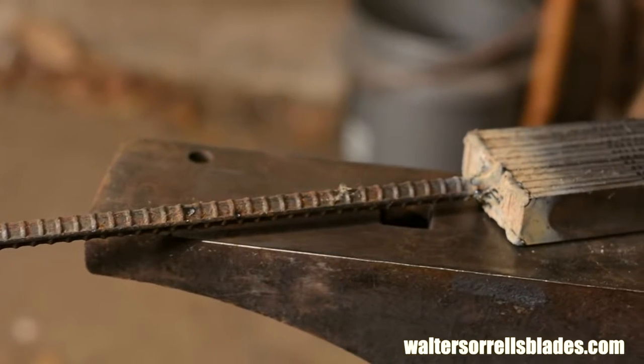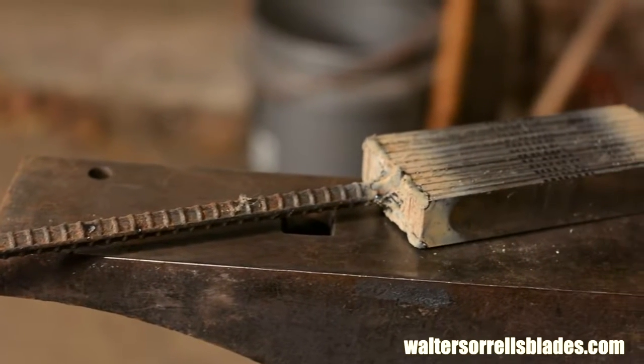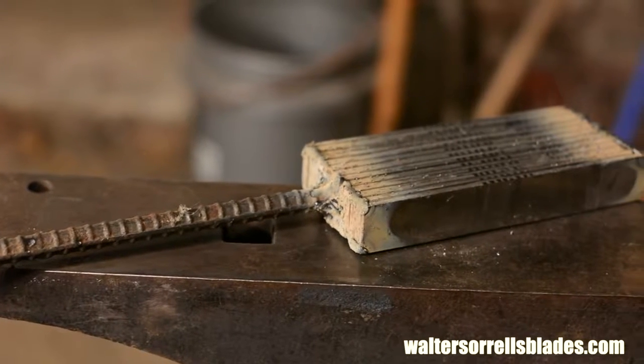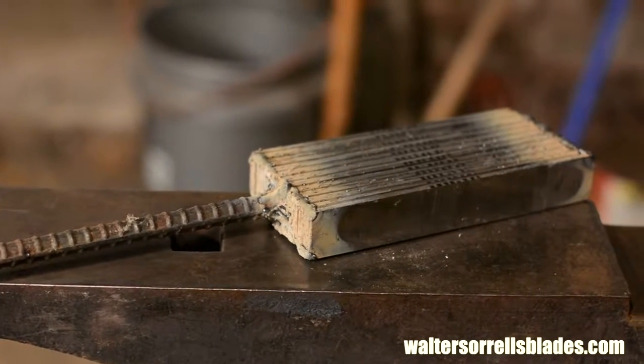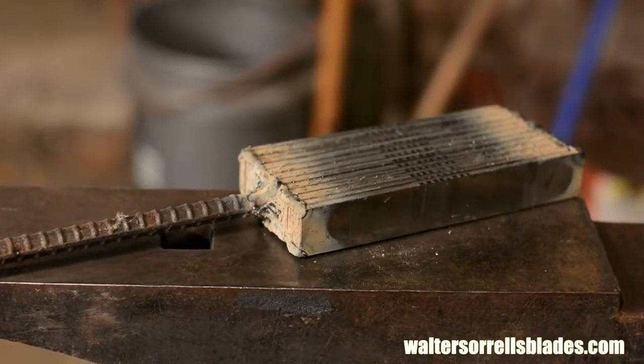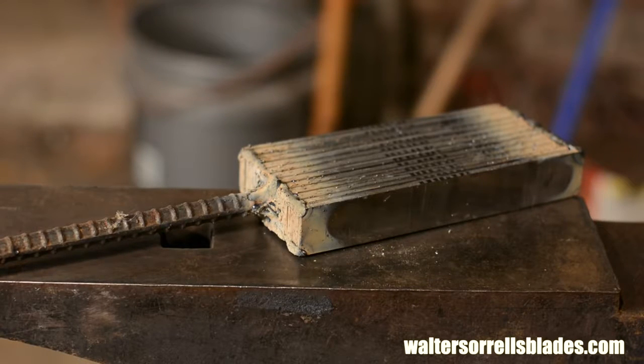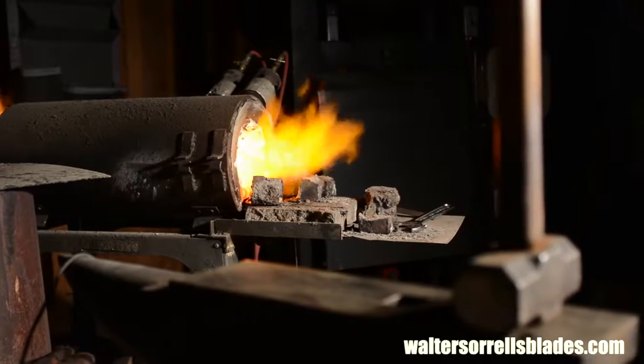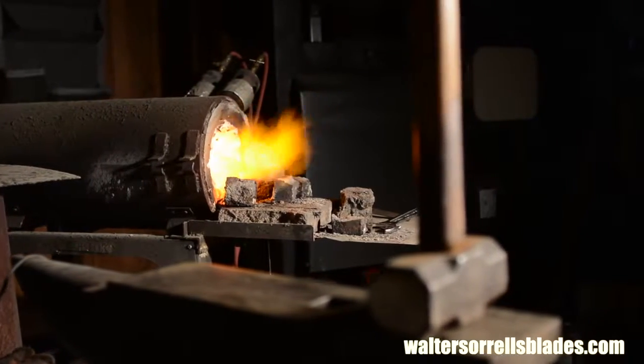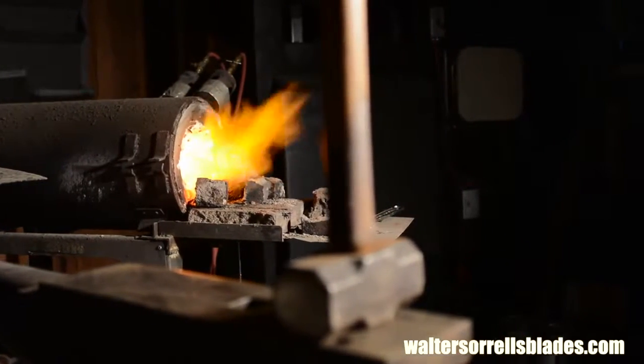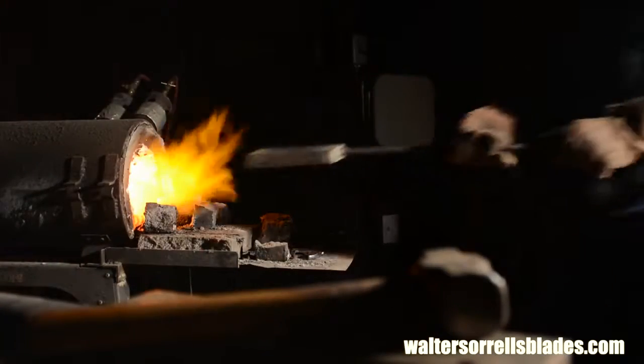Something to be aware of is that any weld material that gets into the billet will contaminate it, leaving bright little streaks, so don't overdo the welding. Just enough to keep the billet from busting apart as it expands during heating. Once I've got the billet welded up, I'll crank up my forge. Once the forge gets hot, I'll put the billet in.